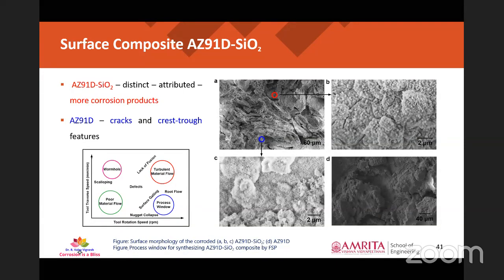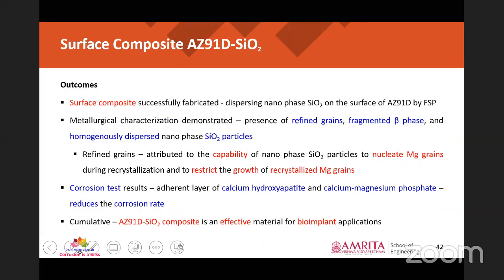So here are the brief outcomes of the research. We have fabricated the surface composite using nanophase silica on the surface of AZ91D by friction stir processing techniques. The metallurgical characterizations demonstrated that the presence of refined grains, fragmented beta phase, and homogeneously dispersed nanophase silica particles have improved the mechanical and corrosion properties of the materials.